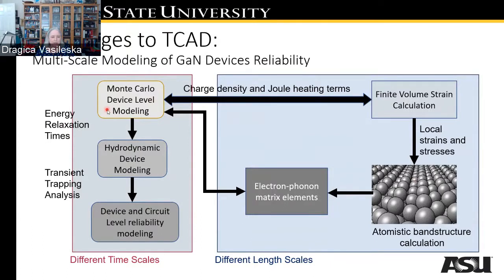So for example, if we want to do Monte Carlo device level modeling, we need to supply to the finite volume strain calculation charge density and Joule heating terms, which can then be used to calculate the local strains and stresses using atomistic band structure calculations, which also provide band structure and the electron phonon, for example, matrix elements that are fed back into the Monte Carlo device level modeling.